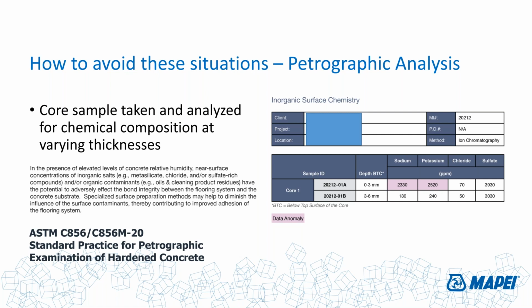Ideally, the best way to do this, and no one really wants to hear me talk to you about this, is that petrographic analysis of a concrete slab is really a good idea. Here's an example on the right side of your screen of a petrographic analysis of a concrete slab, where the people doing the analysis threw up yellow flags, red flags, that said on this particular sample, the first 1/8 of an inch of material had very high levels of sodium and potassium against the normal numbers. Again, you can see 3 millimeters below, it goes to 130 to 240 parts per million, versus something that's almost 10 to 20 times higher on the surface.